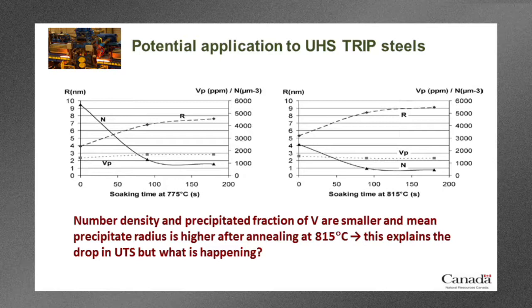So this would be consistent with some kind of dissolution, because the number of precipitates is going down, and growth here. On this graph, it's slightly different at the higher temperature. First thing is that the number density is already much less. So that suggests that in going from 775 up to 815 degrees Celsius, we've lost some of the precipitates that we formed in the lower temperature case. I should mention that the heating rate here was 5 degrees C per second. So also on this right-hand graph, you can see that the amount of vanadium precipitated is a bit smaller, and the mean radius is actually higher.